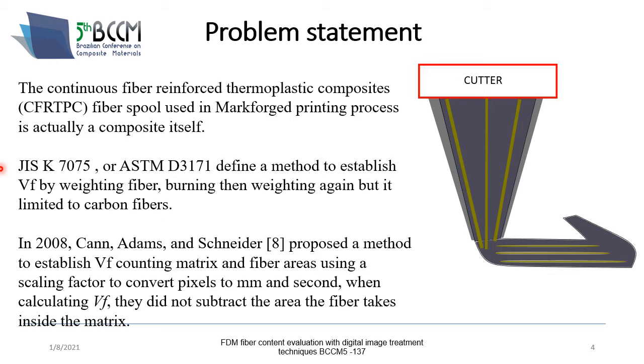There are some methods like the JIS K 7075, which defines a method to establish the volumetric fiber fraction by burning the whole composite and then weighing the remaining residue. This has the problem that it is limited to carbon fiber, which has a great fusion temperature. Other methods are thermogravimetric analysis, and in 2008, Cann, Adams, and Schneider proposed a method to establish the volumetric fiber fraction by counting the matrix and fiber areas using a scaling factor. So, using optical methods and digital image techniques.